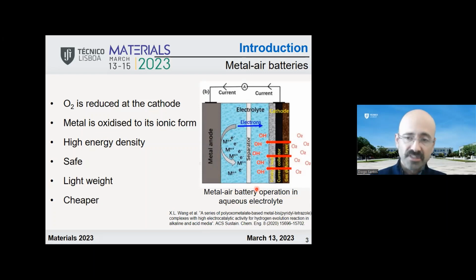We are specifically working on the development of rechargeable metal air batteries. This means that the metal air battery is not just a primary system, but it can be recharged to recover the metal anode. During recharge, instead of the oxygen reduction, you have the oxygen evolution reaction. This has been our main focus for this work: to develop at the same time a material that is active for the oxygen reduction during the battery discharge and for the oxygen evolution during the charge.